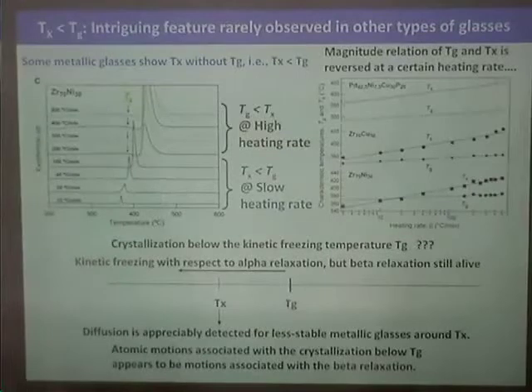Can you not check this in slow cooling? But if you did slow cooling, you would see the Tg first, right? The dependence of the Tg on the heating rate or the cooling rate is not so sensitive compared to the Tx. That's true. This is the experimental observation. For example, we can measure the Tg and the Tx by using DSC thermal analysis. Normally, the Tx is more sensitive to the heating rate or cooling rate. But couldn't you measure these by cooling instead of heating in the DSC? No. If you go to high temperature, it crystallizes. Normally we use heating. This Tg and Tx were measured by the heating process.